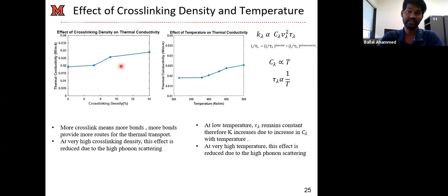But when you have too many bonds, when you increase the cross-linking to a very large degree, it creates aperiodic behavior, which increases the phonon scattering. When a phonon propagates, it soon gets scattered by other phonons because of the aperiodic nature of the polymer. So when you have more bonds and more routes for the heat to transport, too many routes exist, and it reduces the heat transport at a very high cross-linking density.